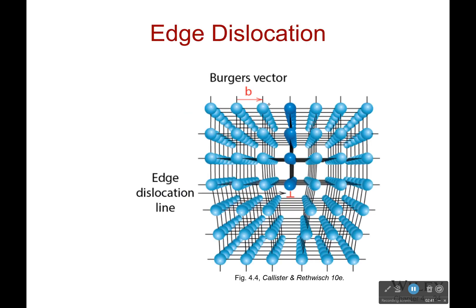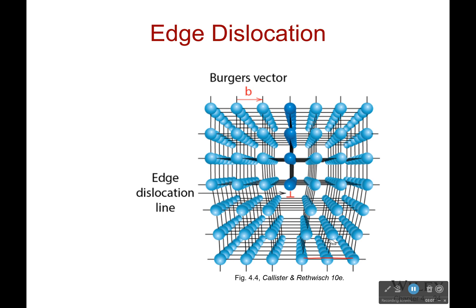This is an edge dislocation. What you can see is everything's fine for these four rows. But then we get to row number five, and we're missing some atoms. Where did they go? They're gone. And because of that, it eventually fixes itself - they're going to come in there and there's no distortion anymore down here. But in this area you're going to see that there's distortion. Now, that distortion continues into the page, or out of the page, depending on what we're looking at.